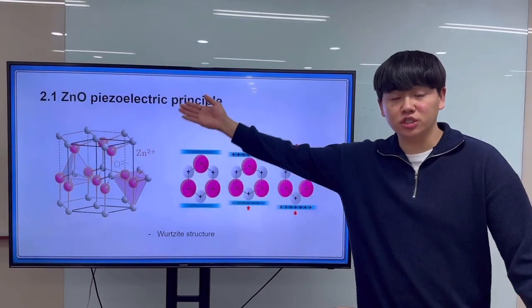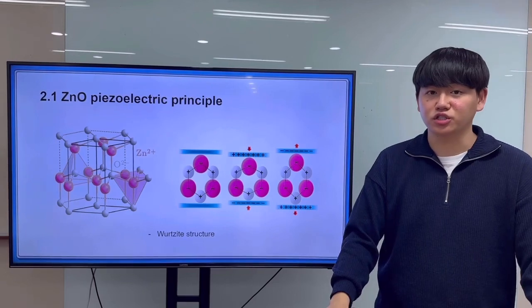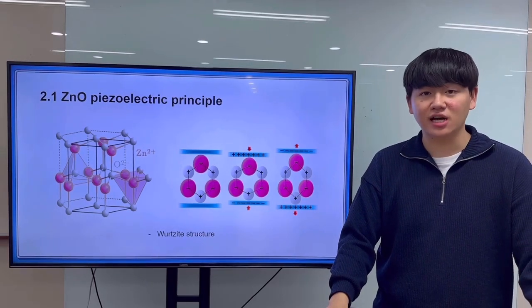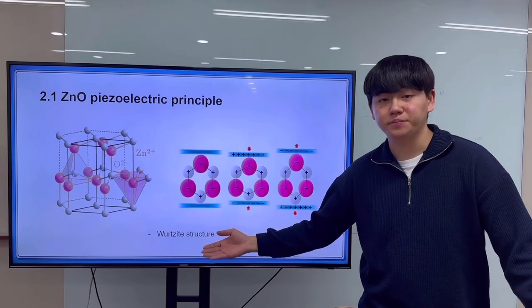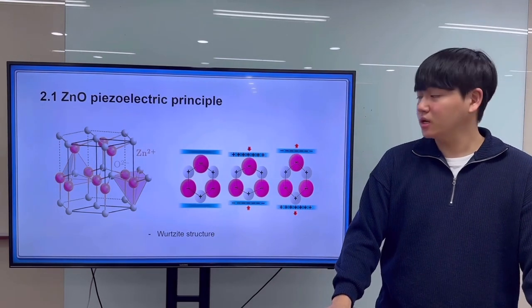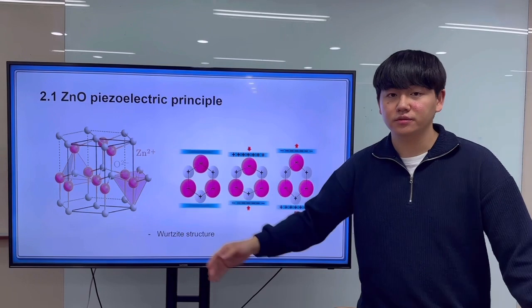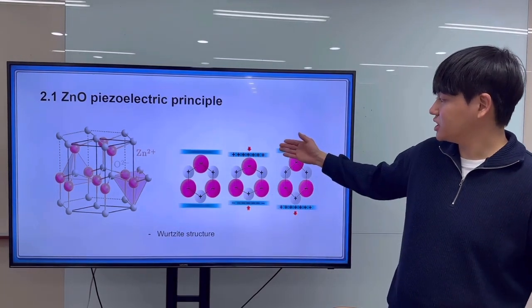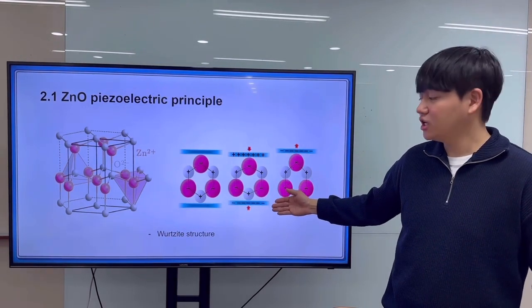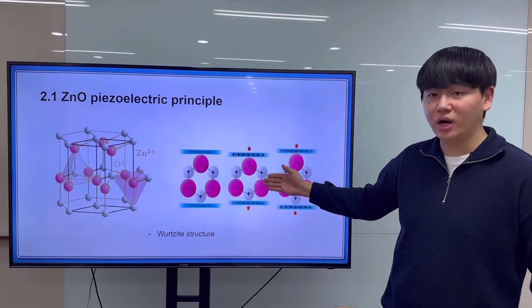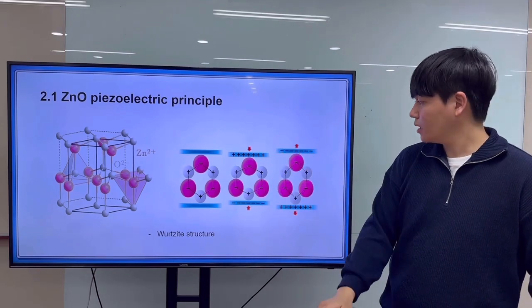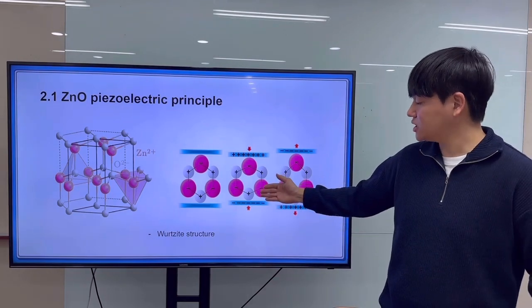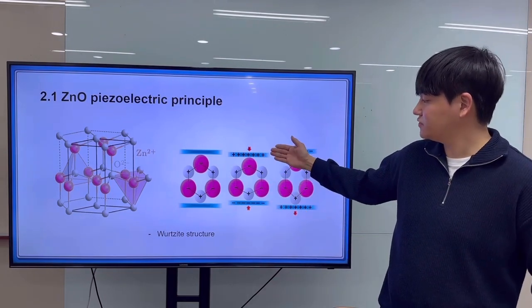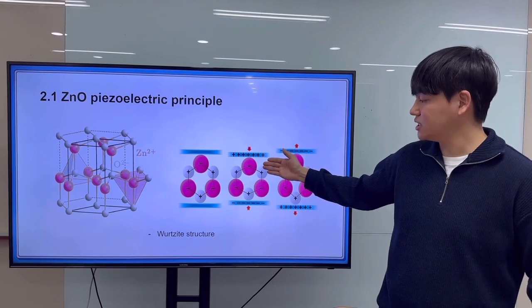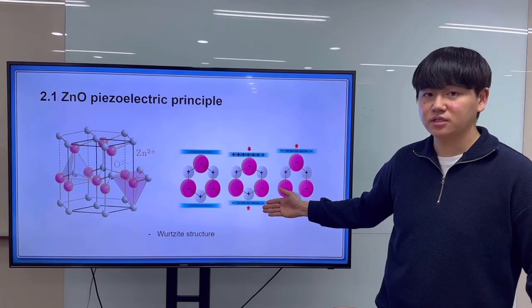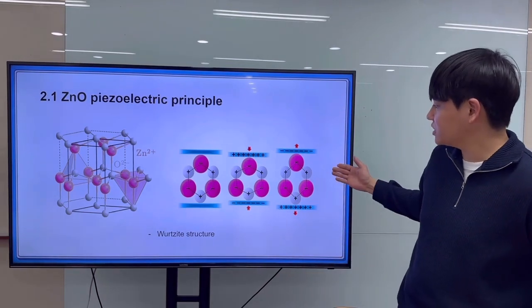First, we chose zinc oxide as a material for our research. The crystal of zinc oxide has a wurtzite structure. It is a hexagonal system as shown in this figure. If you apply force up and down to make a voltage, the pink dot will go down and the white dot will go up. Because the white dot is positive, the upper side will be positive, and because the pink dot is negative, the lower side will be negative. And when we release our force, it will be opposite.